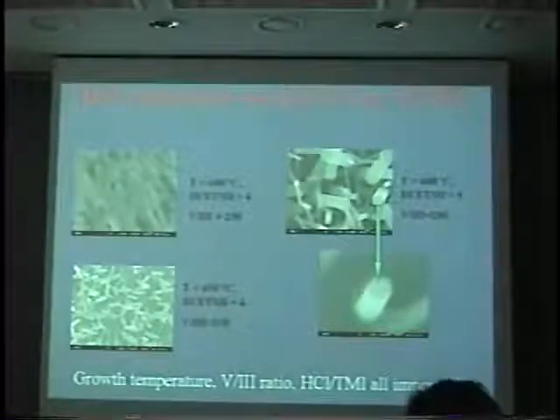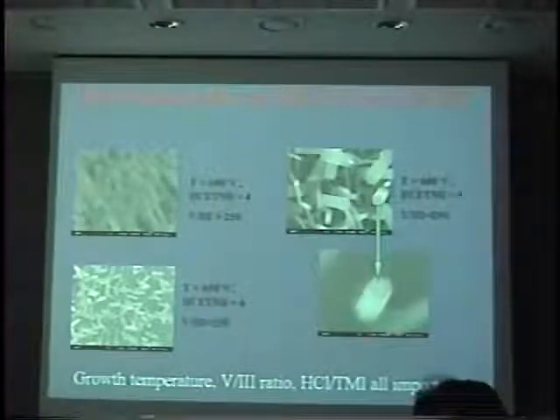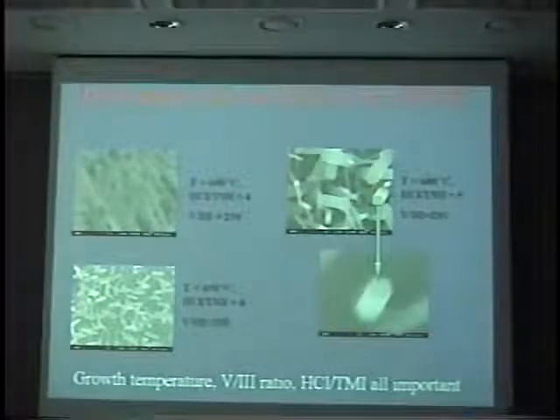I'll just end with one slide. One of the things we did was be able to grow it. We had to get rid of the indium droplets that would form. We did that by adding HCl to the system very nicely. But in fiddling around with this, we found that under certain conditions, we could grow nanorods. These are very nice hexagonal solid nanorods of indium nitride. And so we're working on these materials now, and just last week we put a